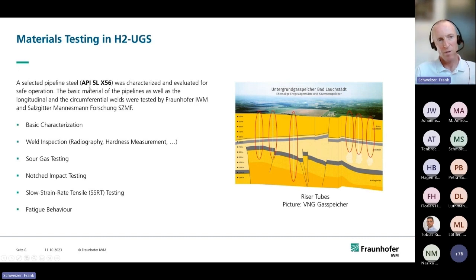And in the consortium we selected the pipeline steel X56 to evaluate, and we characterized it by basic characterizations for steels. We did weld inspections, and you'll see slides of sour gas testing, notch impact testing, slow strain rate tensile testing, and we also look at the fatigue behavior, because you have the hydrogen coming in, so you have pressure inside of the tubes, and you have the hydrogen coming out with the release of pressures. So you have cyclic deformation on the steel tubes. And all the material testing was done by us, Fraunhofer IWM, and by Salzgitter-Mannesmann Forschung, SZMF. I highlighted in the slides what SZMF and what we did.